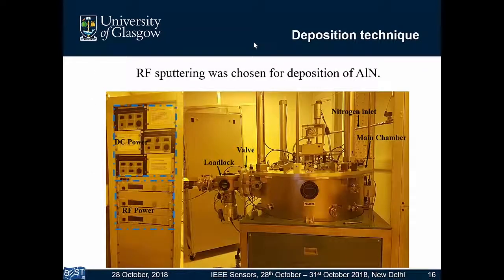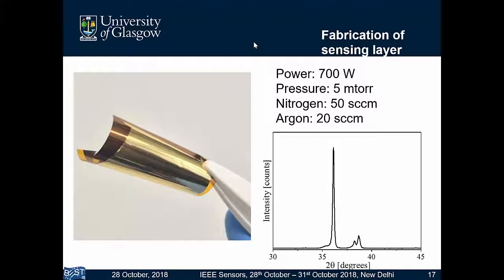considering the process parameters, which are the pressure of the sputtering chamber, what RF power we are going to give to the target, the composition of the gases in the chamber, and the temperature. The temperature we kept at room temperature because our substrate was polyimide and we did not want to damage it. We used magnetron sputtering and sputtered it on a polyimide foil. These are the parameters which we used, so 700 watt, and these are the best recipes which I am showing here. We tried many other process parameters as well.